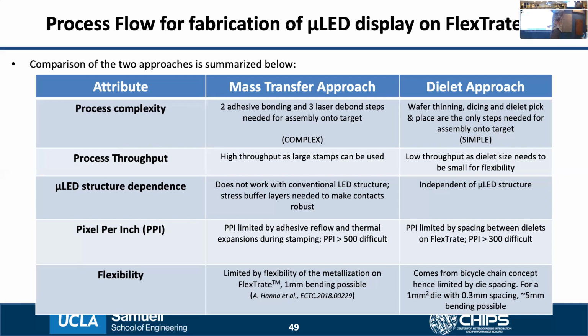So the FlexTrate that we typically make, for example, for this particular case, is 500 microns thick. And so 1 millimeter bending radius would be almost equivalent to folding the sample. In our particular test setup, 1 millimeter is like the minimum bending we can do without breaking the wires. The PDMS is an elastomer, so it can actually stretch. But when we try to bend the wires too much, then the stretching of the underlying PDMS kind of cracks the wires. Yeah, but that's a fatigue issue.